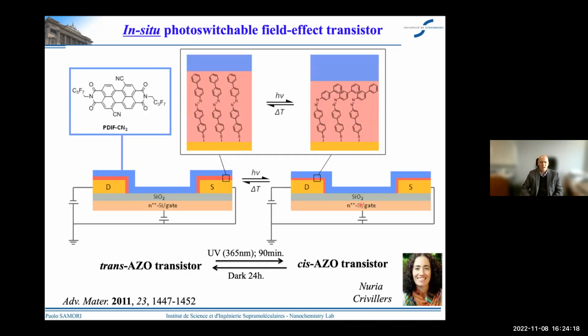And therefore, Nuria Crivillers, when she was working in our lab, reported a very nice experiment in which we took a bottom gate, bottom contact field effect transistor. We coated the gold drain and source electrodes with the SAM of the very same azobenzene, and we put in the channel an air-stable N-type derivative. By triggering the isomerization with UV light, we can reduce the thickness of the organic layer for the injection of charge from the electrode into the semiconductor. And we can also go back to the initial case either thermally or with visible light. And therefore we can have a photo control over the operation of the field effect transistor.